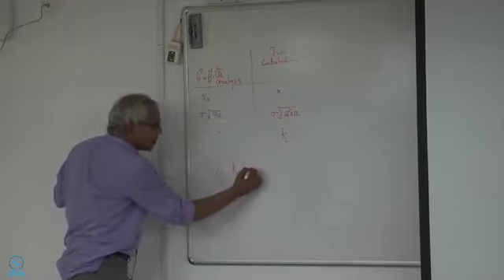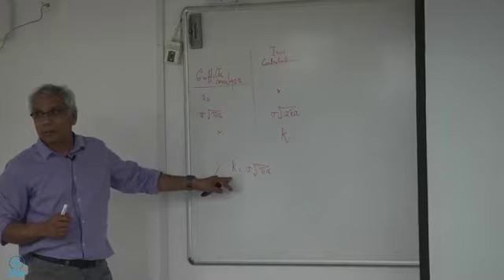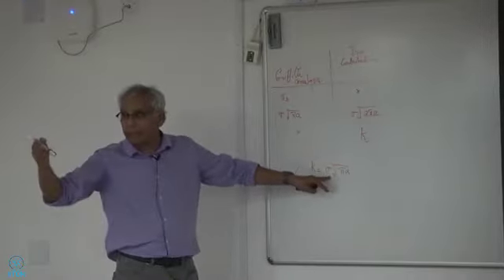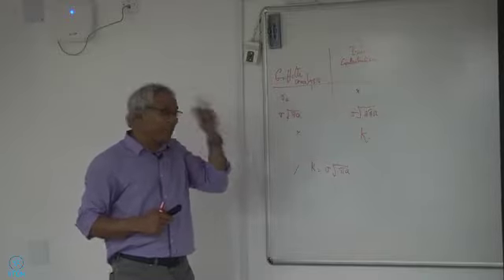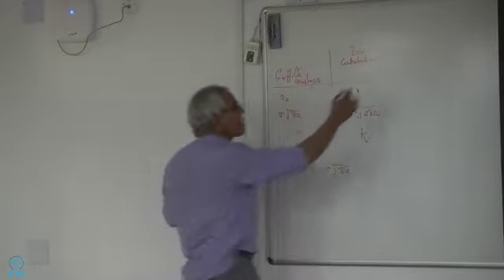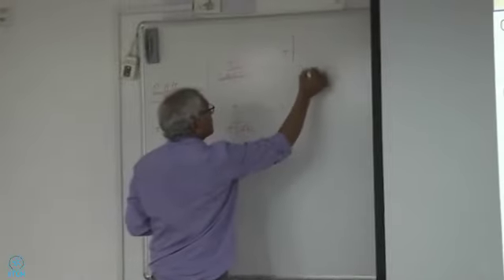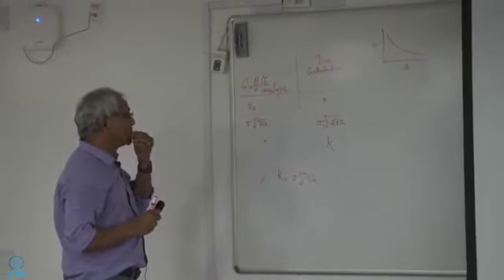Then they said, okay, let us relate K is equal to sigma times square root of pi A. Stress intensity. Not the stress concentration factor, but stress intensity is equal to applied stress times square root of pi times the crack length. And this crack length idea came from the scratches from Griffith's glass work, right? For different scratches. This was the birth of fracture mechanics. All this happened during the early 1960s.